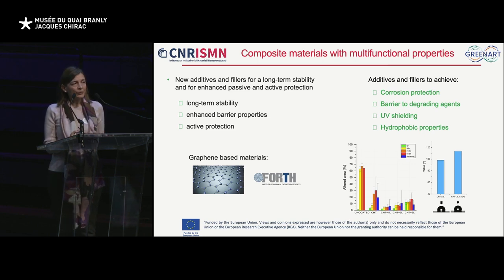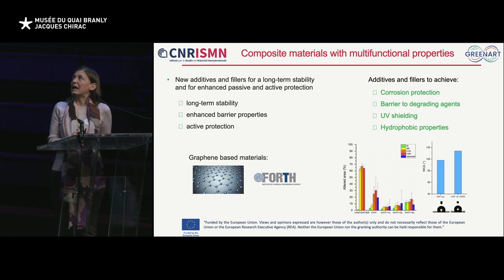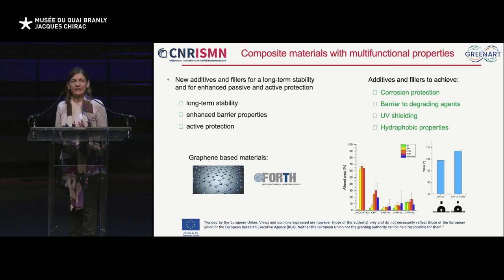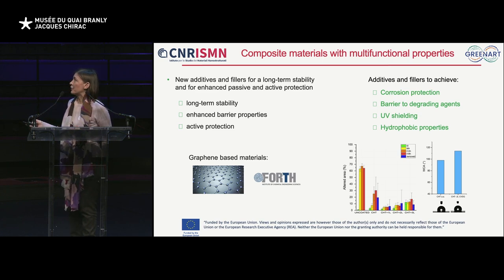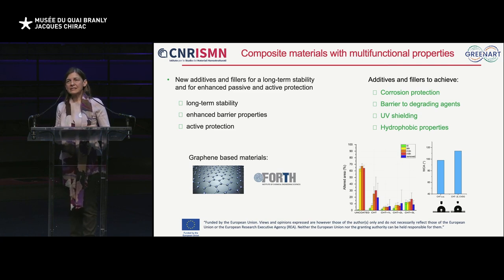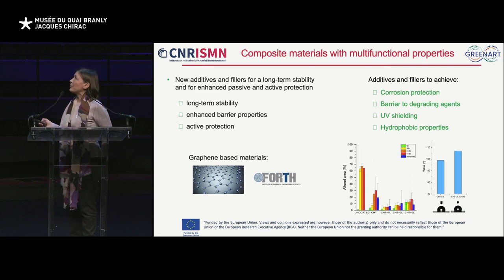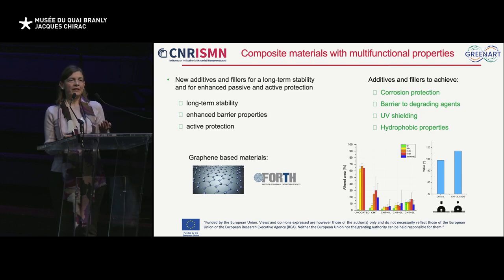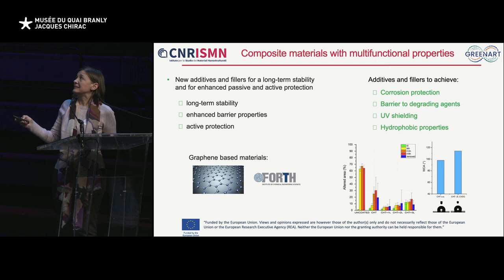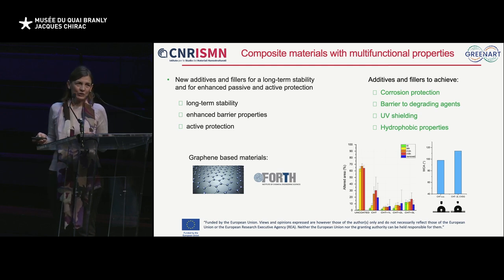So to further improve the protective efficacy, we included in the formulation different fillers, like 2D materials and graphene-related materials that we received from the FORTH group. And we used two different approaches. In one case, the 2D materials were included into the formulation. Another approach was to apply a graphene overlayer on the surface of the biopolymer coatings applied on metals, in particular on bronze coupons. And here I just show the results of the second approach.